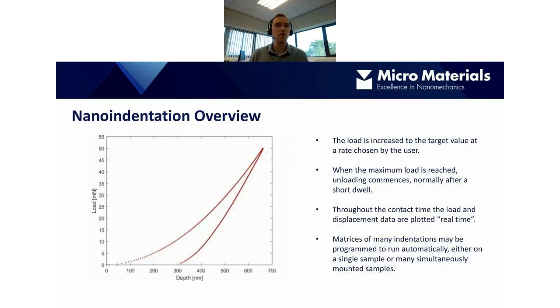Okay, so an overview of nanoindentation. This is a typical nanoindentation curve, or what we call hysteresis, in the graph here. We plot the load on the y-axis, usually in millinewtons, and we plot the depth or the displacement in nanometers on the x-axis. We can see this is a typical indentation that we might get. It looks to me like a fused silica indentation, which we use as a reference material.